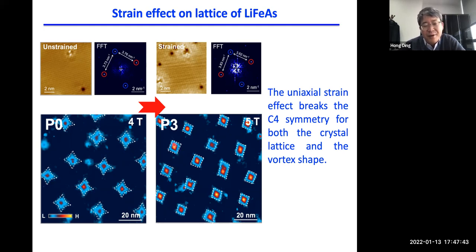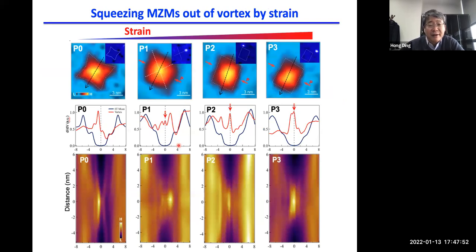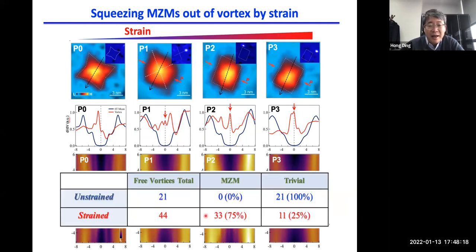So we apply the strain, this becomes a rectangular lattice, and we also see the zero bias peak emerge once we apply strain. It's remarkable. We fully anticipated this would happen, but once it did happen, we were kind of overwhelmed by this result. And this also happened in many cases. For the free vortex in the unstrained case, we have 0% zero modes. We did 21 vortices. In the strained case, we did 44 and achieved 75%. So statistically, it's very significant. We've increased from 0% to 75%. For the rest, we think it's due to non-uniform strain.